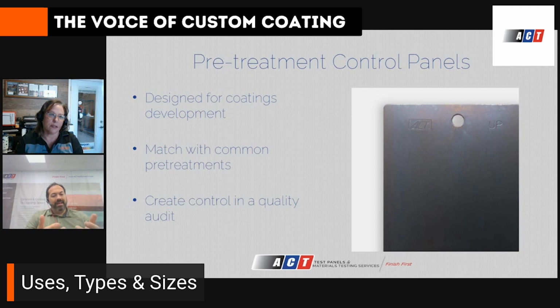Okay. The bend tests, in a lab, they'll use a machine that's called the conical mandrel bend. So it looks almost like a cornucopia, right, from our Thanksgivings. It's got a small end and a big end, and you put the panel down in that, and it's got a bar, and it pulls that over. And so you get this loop. And what you're looking for there is along that bent edge, do you see any cracking or breaking of that substrate? So powders will have so much elongation, they won't have infinite elongation, but that's what they're looking for.